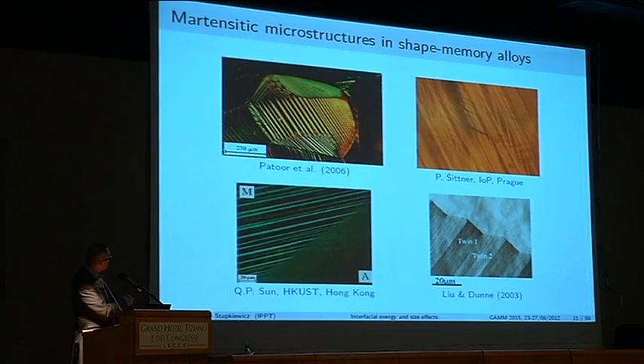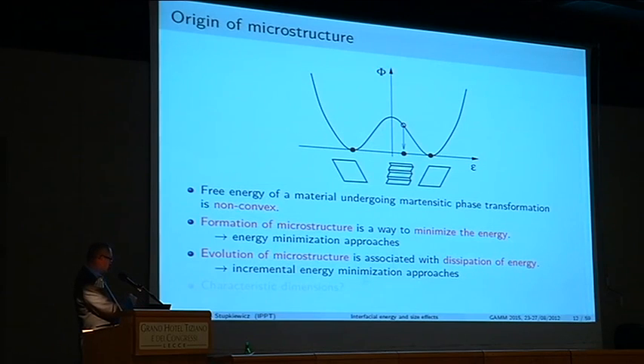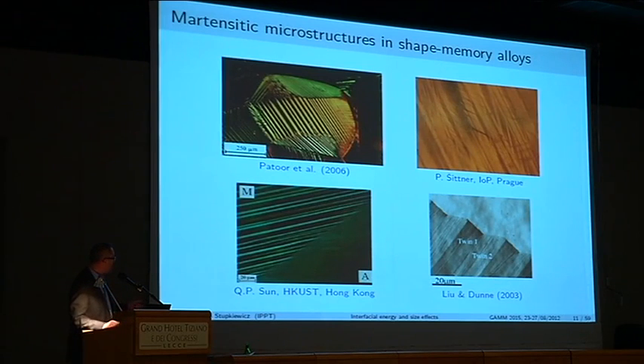And then if you look deeper into the martensitic phase, not in this particular material, but in many cases, the martensite itself has a substructure, which is twinned structure. What seems from far away to be uniform material, if you look close enough, very often has a substructure of a laminate. These are two twin-related variants of martensite, and here you see a beautiful sharp interface, macroscopically sharp planar interface between austenite and twinned martensite. And here you also see two examples of much more complex microstructure that may occur in these materials, and there are many, many more if you look in the literature.